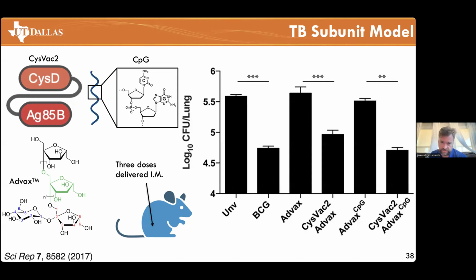But the ultimate measure, of course, is how well they do in terms of log reduction of an infection model. And you can see BCG. So this is unvaccinated. You get 5.5 log CFU in the lung. BCG does a great job in mice. It does not do well in humans. But you can see here that when you add this clinical Advax, you get a reduction compared to the unvaccinated. And that's really what we're looking for. We're not looking necessarily to compete with BCG, but a lower log reduction would be very promising. But on a mouse model, our initial assay is simply efficacy because we have to move to different animals that are more representative, including large primates, which is going to be better, or guinea pigs.